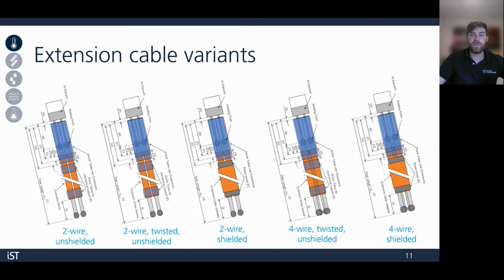So these extensions are performed with laser welding, and we typically add a TFE-R shrink tube around the weld joints and then again around both wires here. You can see in blue. Some additional ones are added to protect the twisting of the cables. The insulation wire that we're using is also ESCC qualified according to detail spec 3901-19.